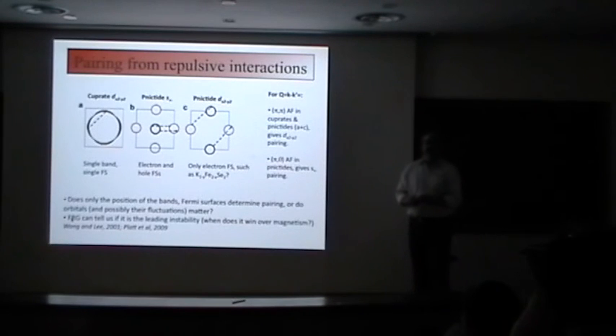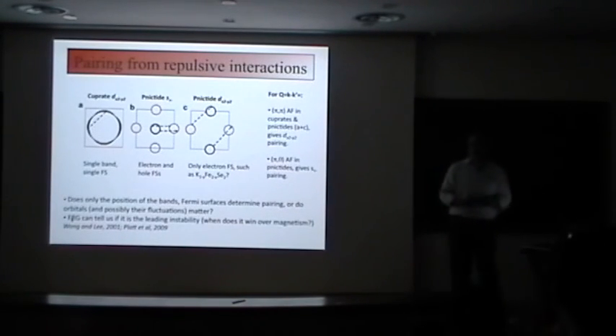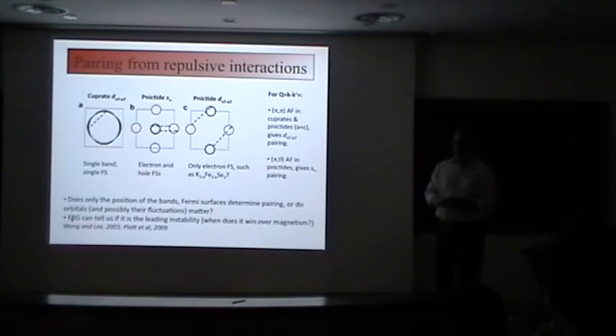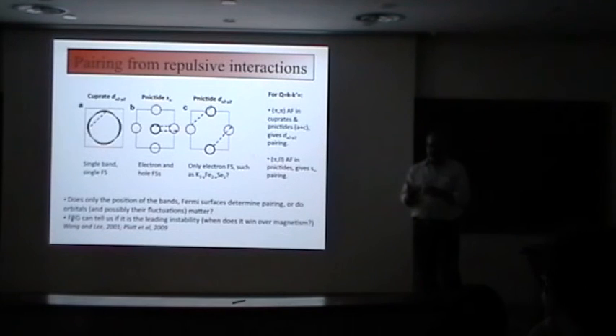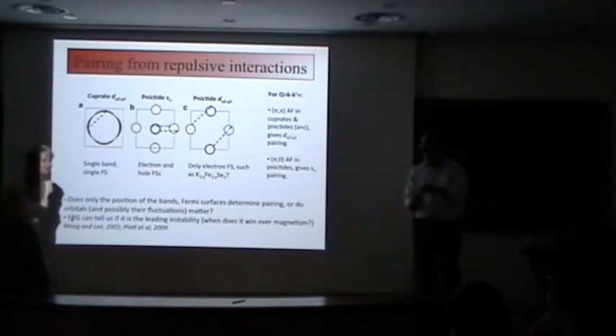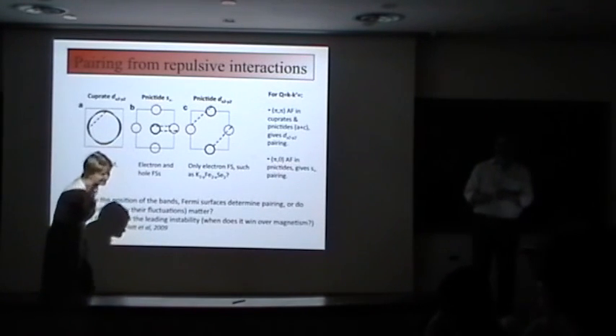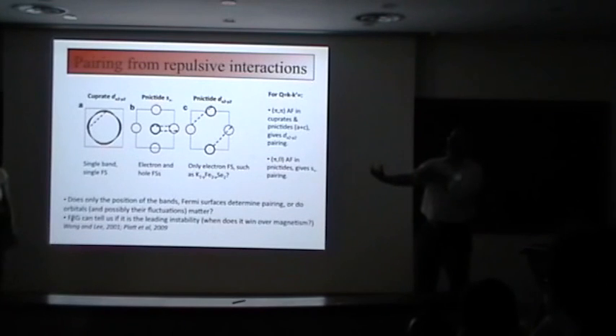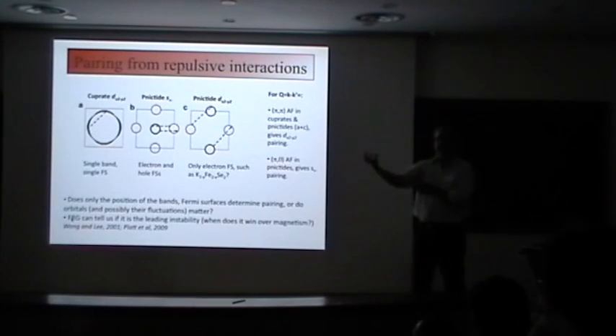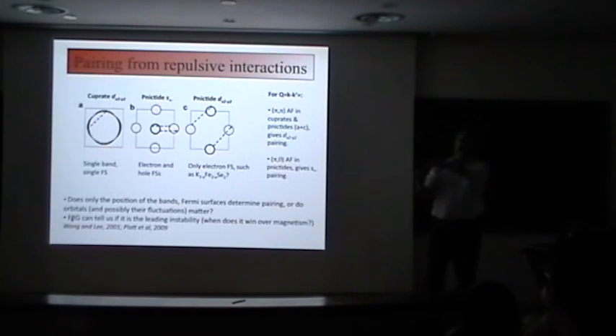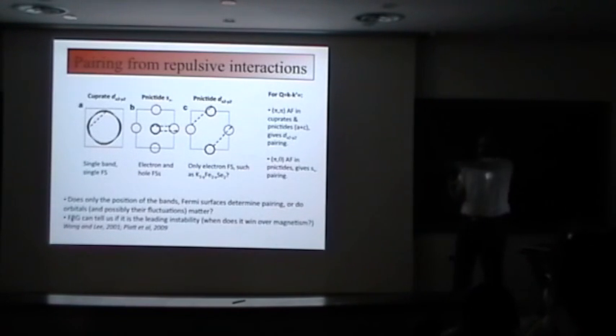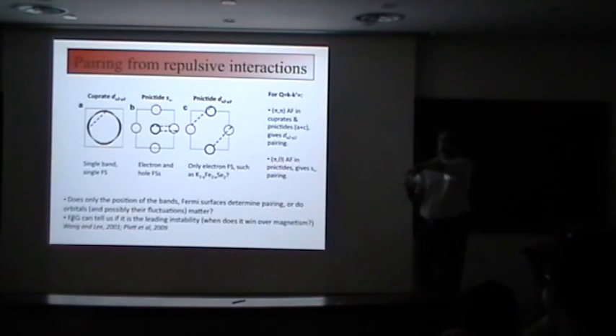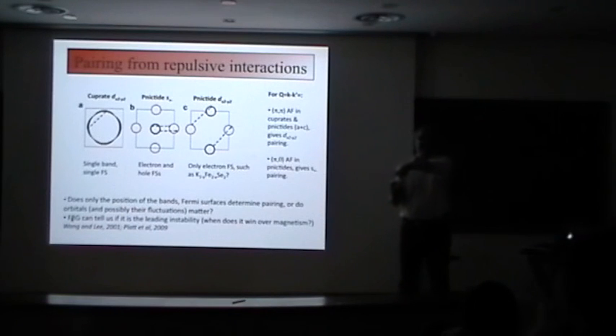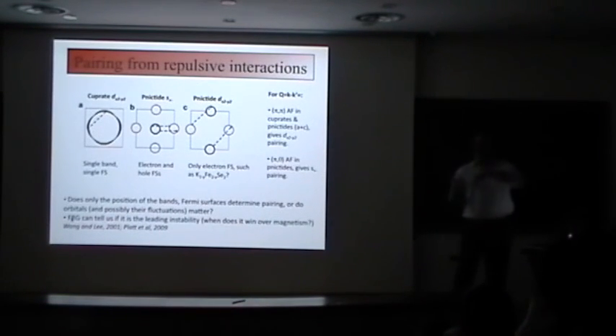Is there any progress on understanding that dichotomy? Yeah, so what Peter is pointing out is the measurements which have been done by the Japanese group, when one takes very, very small samples, so they're all within one particular domain, and then you don't have any applied stress. There may be some strain effects due to the size of the crystal itself, and torque magnetometry measurements have been done and have seen this anisotropy at high temperatures, much above the structural transition. That's the last word I've heard on that.